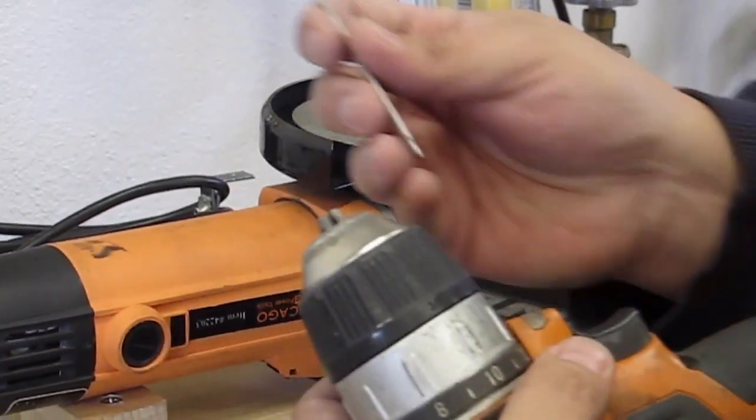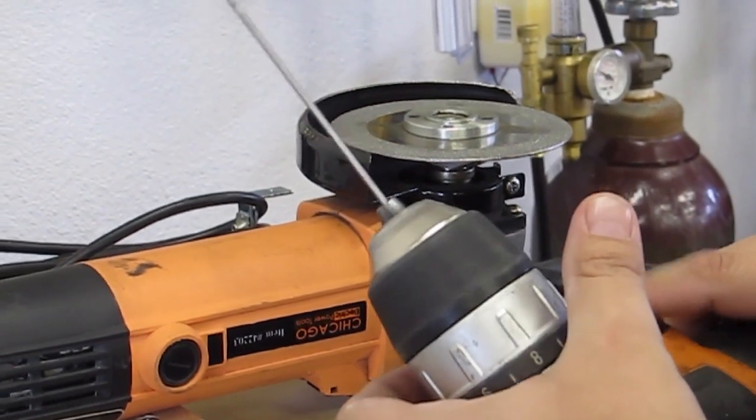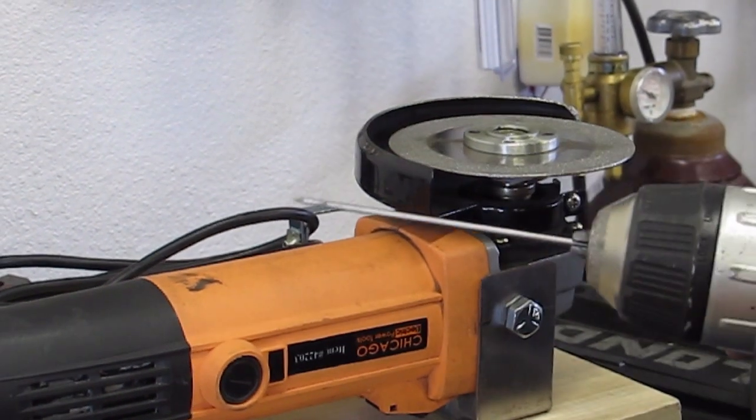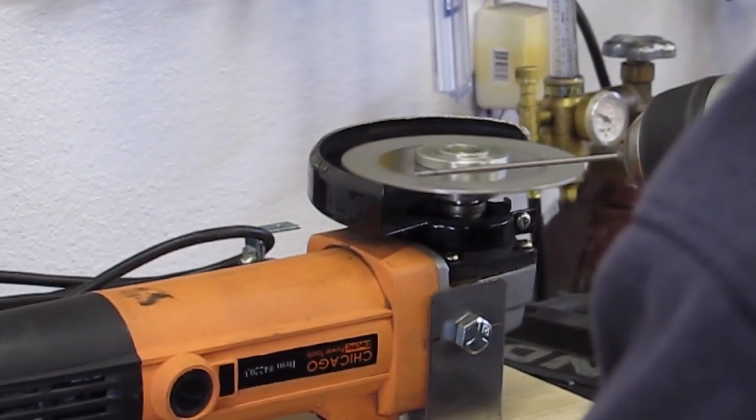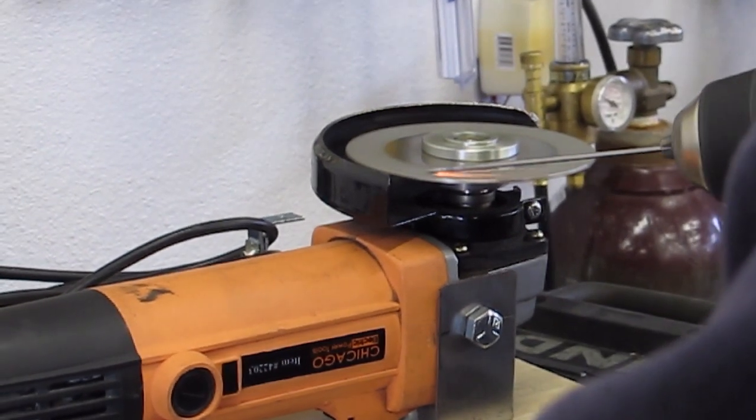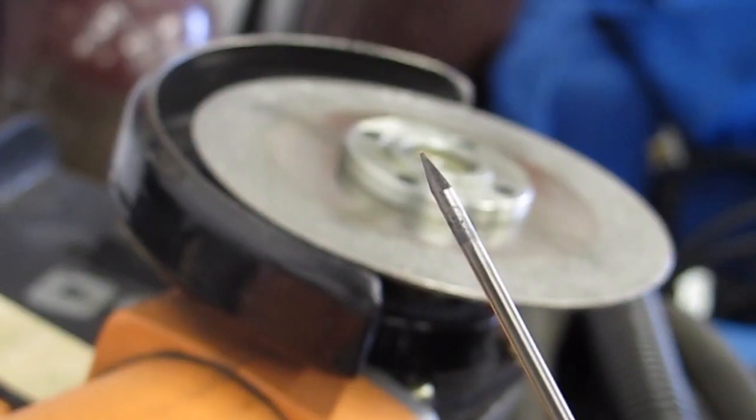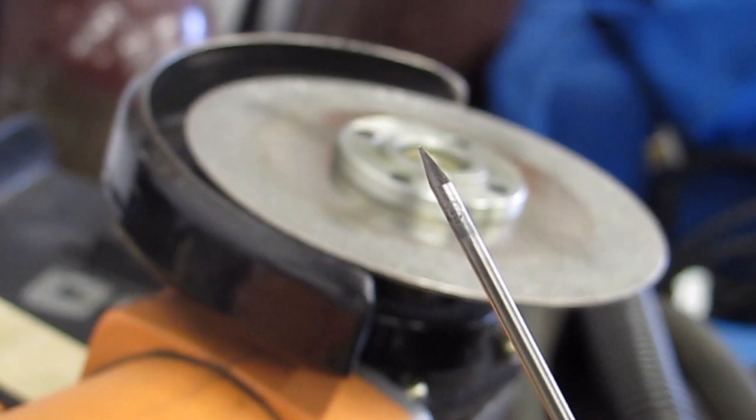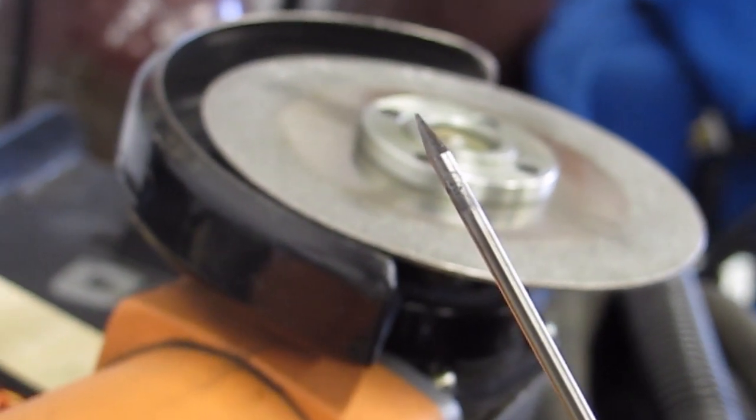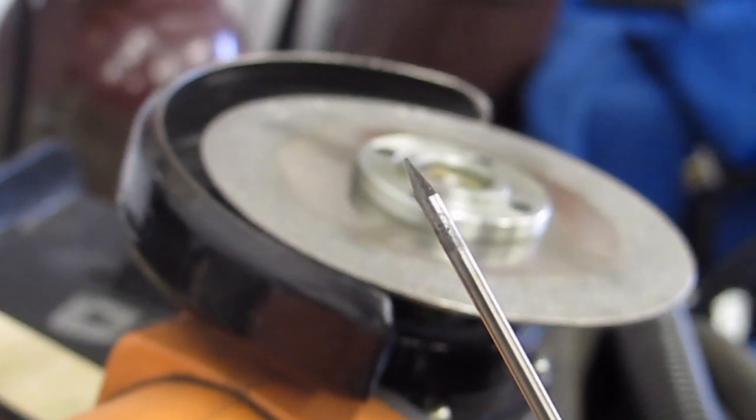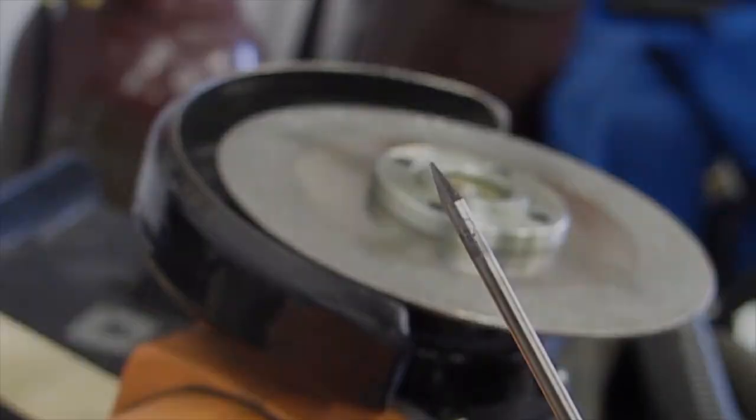So in order to make this really work, I like to use a cordless drill and I take my tungsten and I chuck it up into this cordless drill and you can see it now spins. So this is going to get kind of loud. You won't hear me here, but I'm going to flip the switch and I'll show you how I grind this tungsten. So there you have it. You see I got a real nice point on this tungsten which is perfect for an inverter style machine. No need to snub the tip. A nice sharp point is always good. And you see how quickly that works. So this is really a time saving device to have a homemade tungsten sharpener like this.